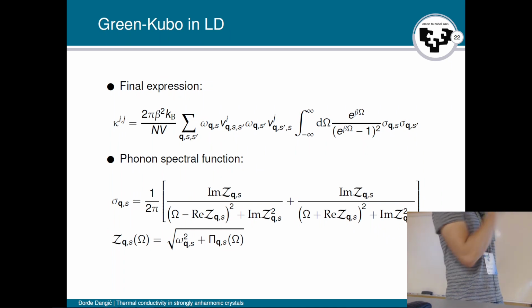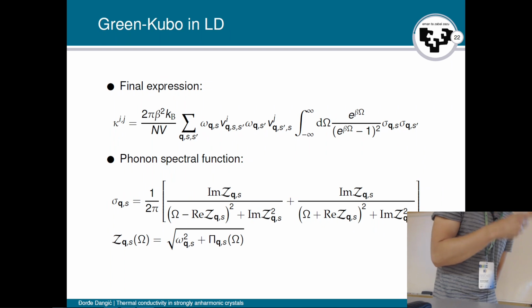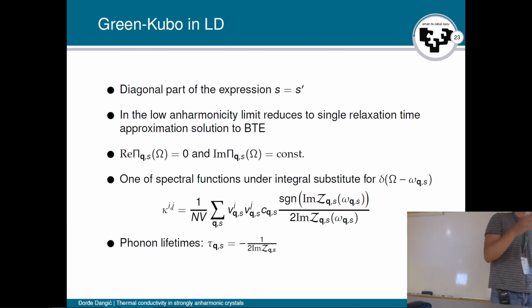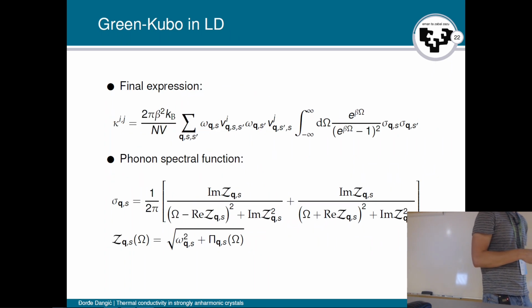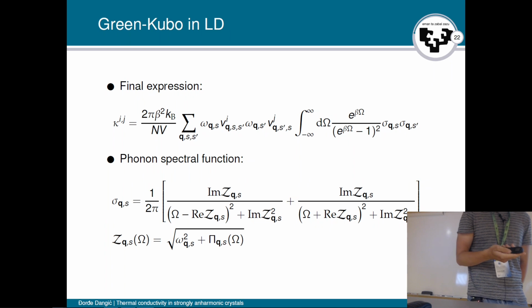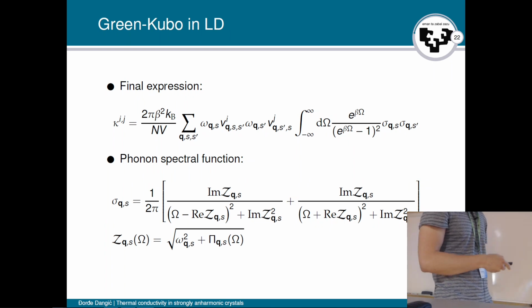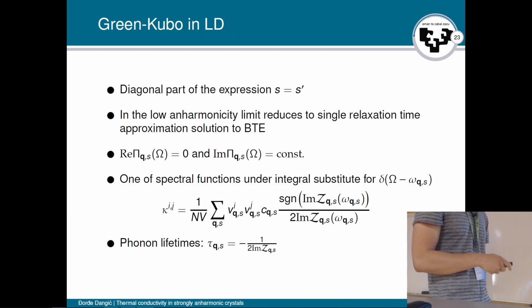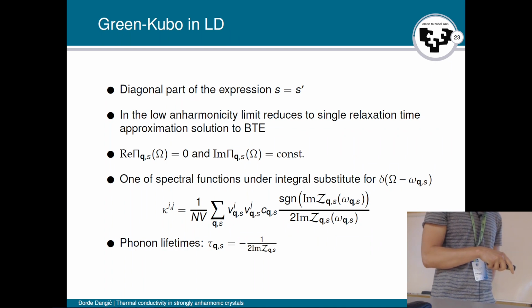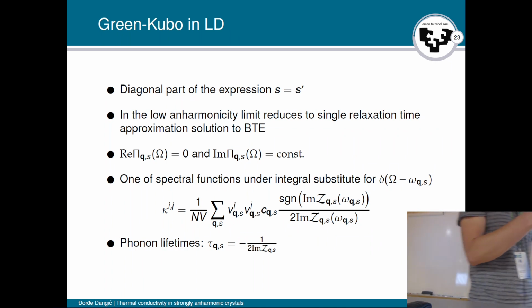Now that our spectral functions are Lorentzian with very small line width, we can imagine them as a delta function. And so we have here one of them as a delta function. And what does the delta function do to the integral? It kills the integral and replaces all the integration variables with the real part of the z function, which in this case is just omega, right? Because the real part of the self-energy is 0 in this limit. If we do all of this, we have to be careful about the sign of the imaginary part. So we want our spectral function to point up, so to be positive. And if we take care of all of that, we have this expression for the lattice thermal conductivity.